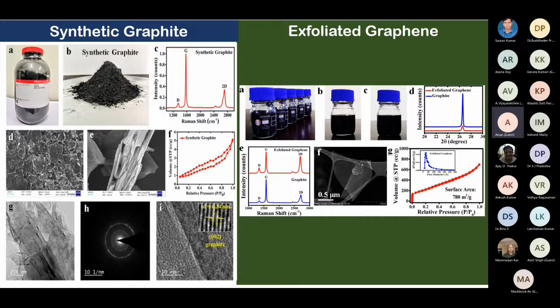In the plasma spray, we tried to put it at high temperature, and we definitely put a shroud there also in the plasma. Once we sprayed the powder particles, we kept the powder chamber on the other side, and then we collected all the powders after the spraying. Once we collected the powder, you can see image A on the right-hand side, where we got a lot of powder in these bottles. After this, we thought it may contain exfoliated graphene,